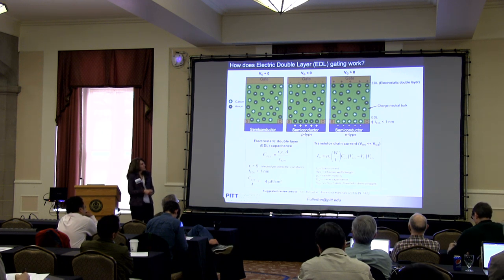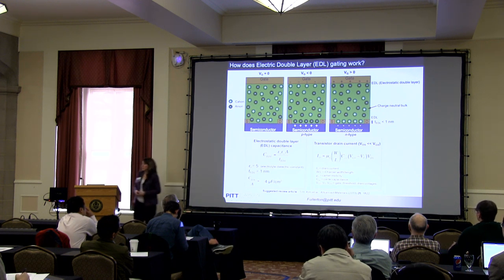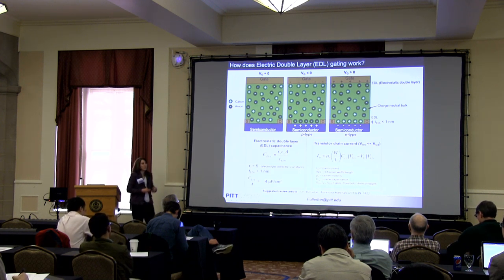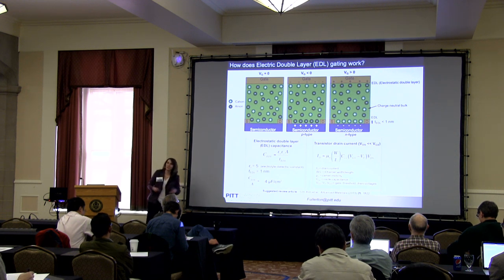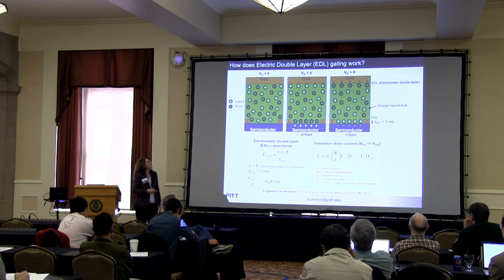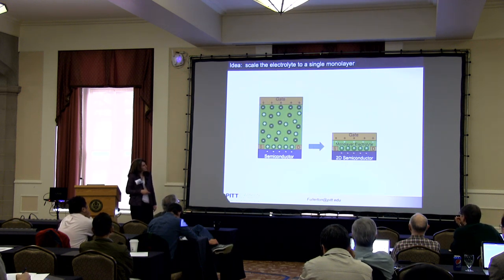and then apply the opposite field to push the ions away into the off state. And what I'm showing here isn't actually just a schematic. These are actually outputs from DFT calculations by our collaborators, showing that when you apply these fields, not only does the lithium respond to the field, but it sort of drags those ether oxygens along with it. You can see how the ring is kind of puckering in response to this electric field.